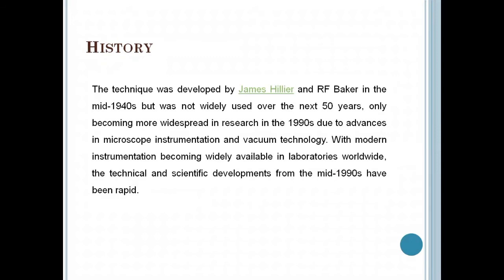The technique was developed by James Hillier and R.F. Baker in the mid-1940s but was not widely used over the next 50 years, only becoming more widespread in research in the 1990s due to advances in microscope instrumentation and vacuum technology. With modern instrumentation becoming widely available in laboratories worldwide, the technical and scientific developments from the mid-1990s have been rapid. The technique is also able to take advantage of modern aberration corrector probe-forming systems to attain spatial resolutions down to approximately 0.1 nanometers, while with a monochromatic electron source, the energy resolution can be 0.1 eV or better.